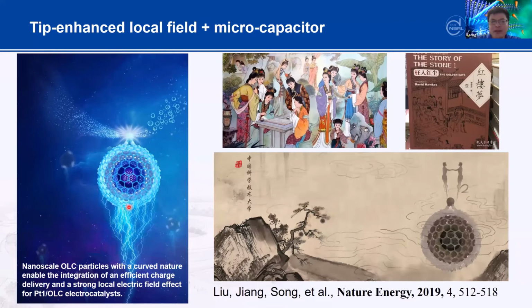Here, as you can see, if you apply an electric field, first they will form some local field, which can absorb the proton here, and the protons will combine together to form hydrogen. But meanwhile, as you can see, this is a carbon onion. A carbon onion is a shell, layer by layer. When you apply the voltage, between two shells, they really can work as a capacitor. So in this capacitor, they can collect the electrons.